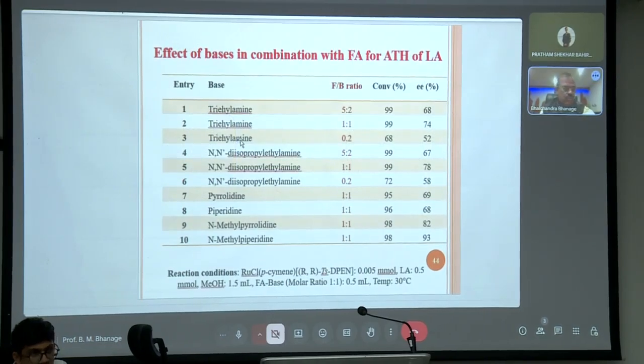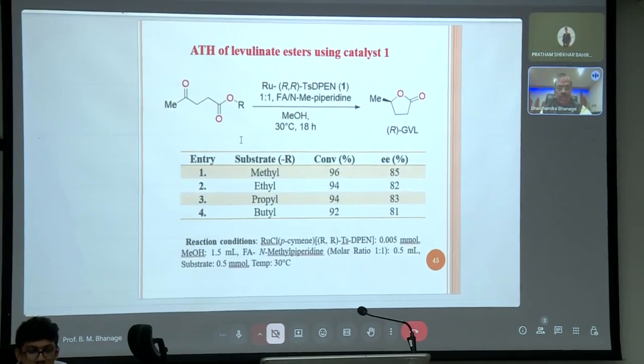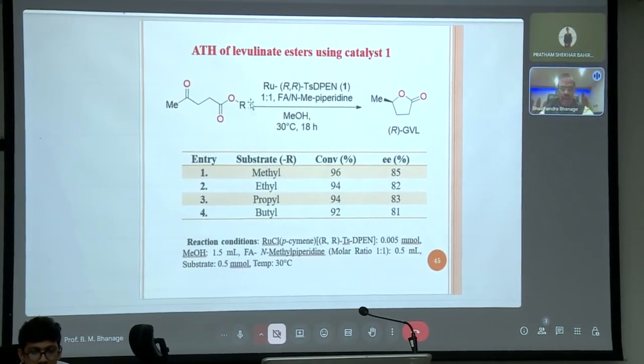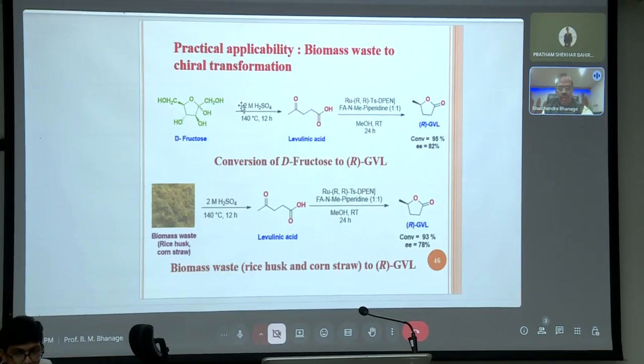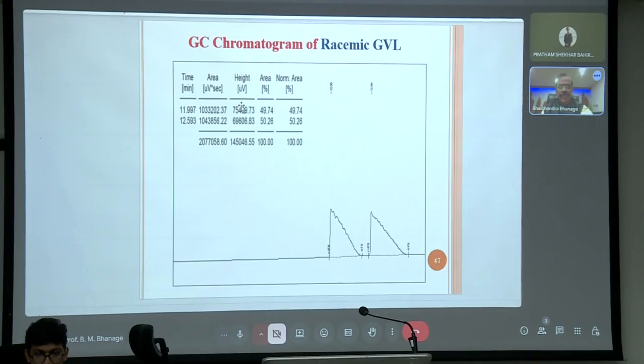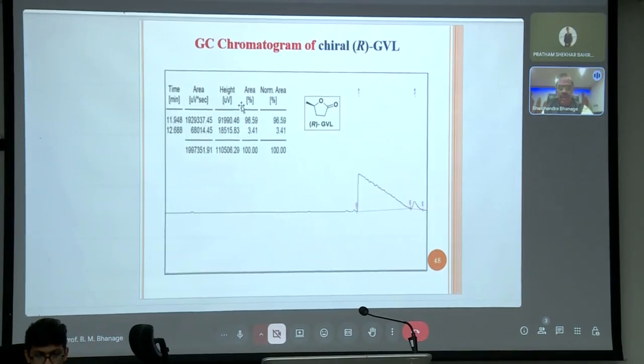And we have also screened various bases for this particular combination, and you can see that the first combination was useful for this particular transformation. So here you can vary this particular R and prepare different types of GVL using this technique. So you can have permutations and combinations of different types of substitutions with respect to R. You can see the GC. This is racemic GVL, and you can see here the GC of chiral GVL. So you can see that this is the enantiomeric excess R GVL which we have produced using this particular technique.